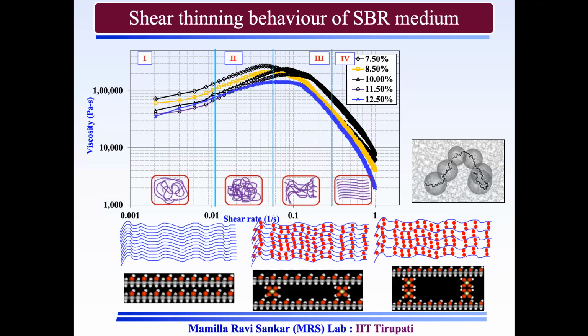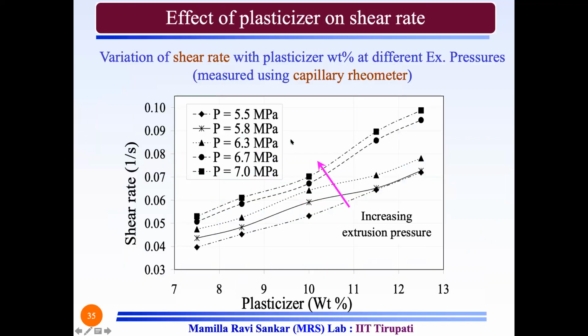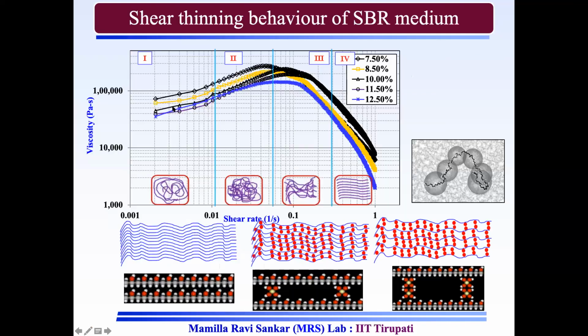That is the ultimate. But if there is a minute breakage, still okay. That means if you see my previous one, my range of experiments is below 0.1 shear rate. So if I see the shear rate ranges below 0.1, I am observing there is no breakage or minimal breakage. That means that my experiments are conducted with the better polymer molecular chains or better polymer networks.